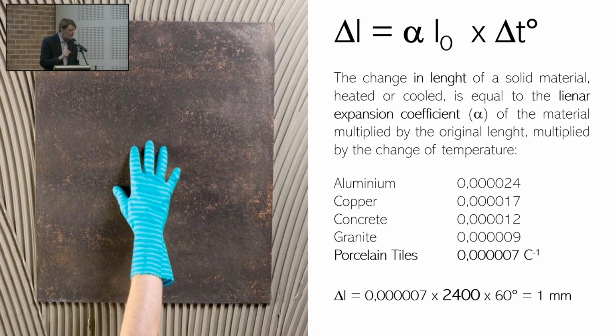Of course, this is a very superficial consideration, because if I want to know whether the tiles move, I need not only the coefficient of deformation but also the size of the tile. You see? The size of the tile. Because the final deformation, delta L, is given by the temperature delta, the coefficient of deformation, but also the size of the tile. Even if the product itself is not very deformable, when I use a 240 centimeter length tile, I have a deformation of around 1 millimeter for this material.